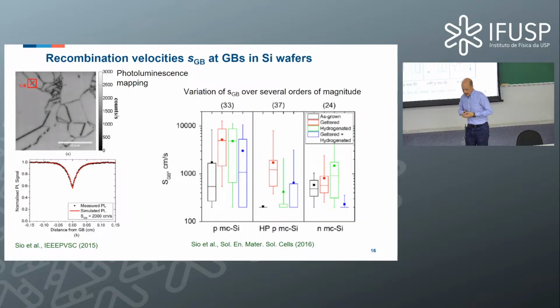When you look at measurements of recombination velocities, there is a publication by Chen and McIntosh from the University of New South Wales in Australia, and they used photoluminescence mapping. So basically, you have photoluminescence intensity across a certain area. This is a multicrystalline silicon wafer, and you can see the grain boundaries because you have enhanced non-radiative recombination at a grain boundary. So the luminescence, which is the radiative recombination, is reduced. And that's why the intensity in the photoluminescence is reduced. Okay?